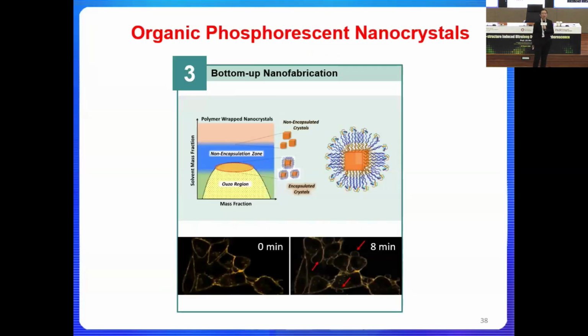After we detour for so long, we understand how to select the molecules and how to dope them. The question is, I still want to bring these molecules into aqueous media so that we can use them for biomedical applications. In order to do that, we really hope to form very small structures, preferably crystalline, so that they can resist water and oxygen in the aqueous media to give us room temperature phosphorescence. So this requires us to develop a strategy to make sure that the molecules can form crystals in the aqueous media, but the crystals will not grow crazy. It has to be confined in the 50 nanometer to 100 nanometer range.